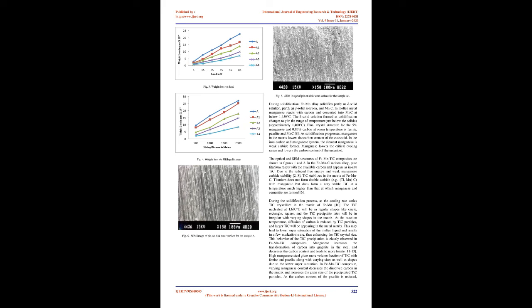The test was conducted. An indication by the load cell, i.e. frictional force, was noted. After finishing the test, the specimen was carefully cleaned, that is, burrs at the edges were detached, and the specimens were weighed again precisely. By applying the weight loss method, the wear rates were calculated. The tests were conducted under varying loads, 5 N to 85 N at 200 rpm for 15 minutes, and varying sliding distance 500 m, 1000 m, 1500 m, and 2000 m at a load of 50 N and sliding velocity of 3.33 m/s.